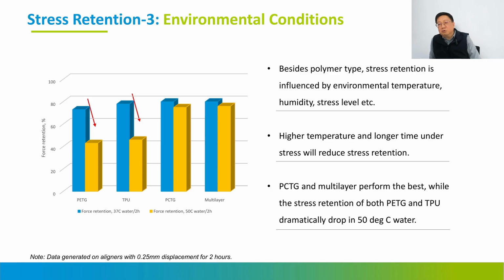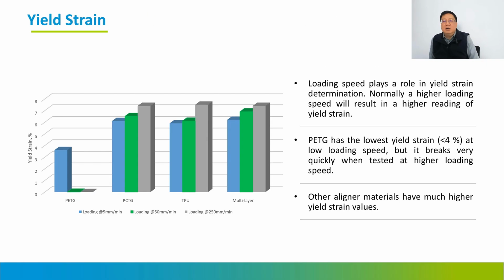And you can also do a test by yourself. For example, you can put different aligners into 50 or 60 degrees C hot water and see which aligner deforms most. If it deforms most, its stress retention is poor. And this is the yield strain. Yield strain means that during the wearing and taking off process, you will strain the aligner longer.